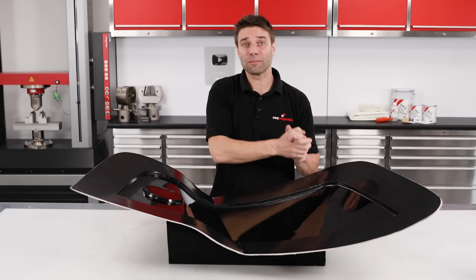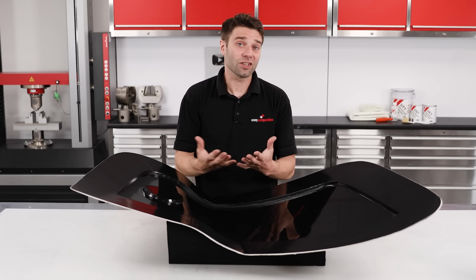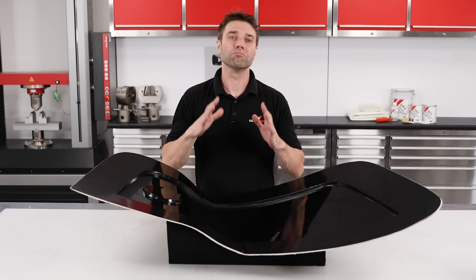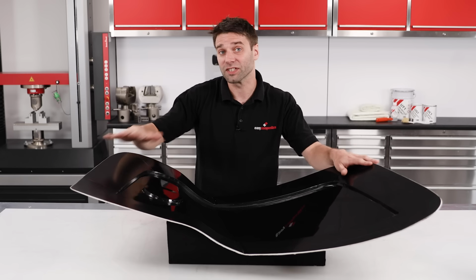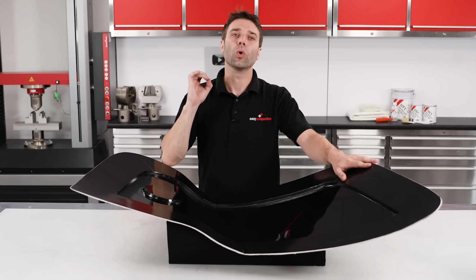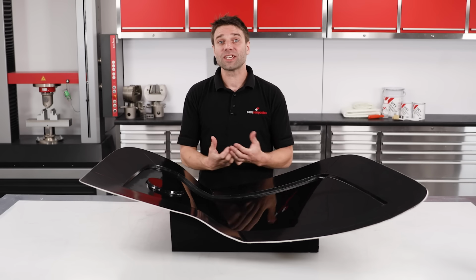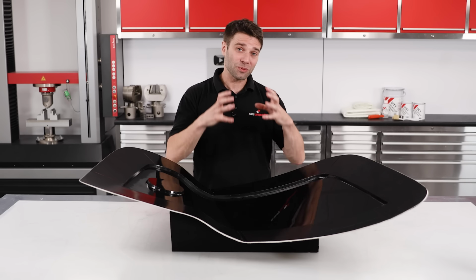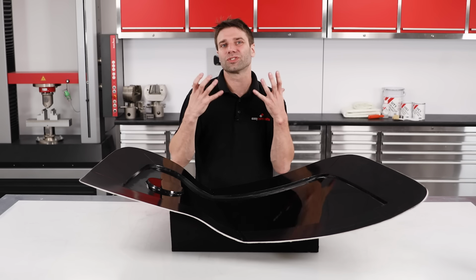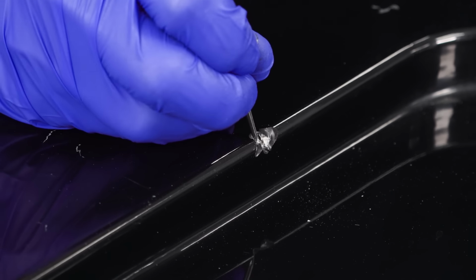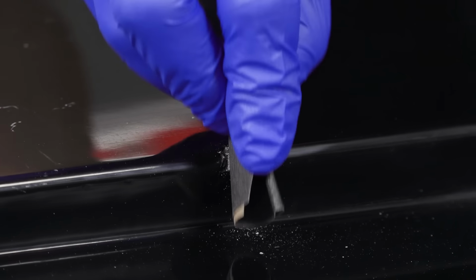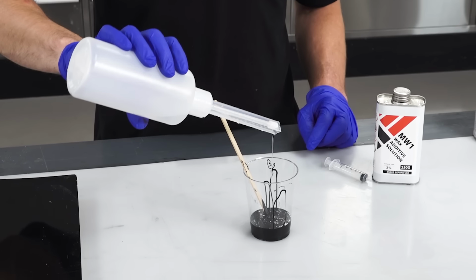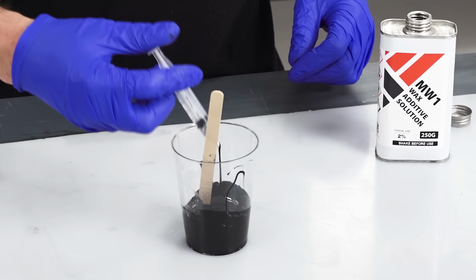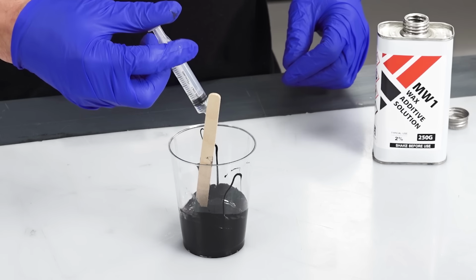So what about damage repair then? If you do find that the gel coat is chipped or cracked either during mould production or later when the moulds are in service, then that damage should always be repaired before use. Fortunately, this is generally a very straightforward thing to do. The damaged area should be worked down first to a good solid base or substrate material. It should then be scratched up and sanded to provide a mechanical key, and then some catalyzed gel coat is mixed up along with 2% of MW wax additive solution.